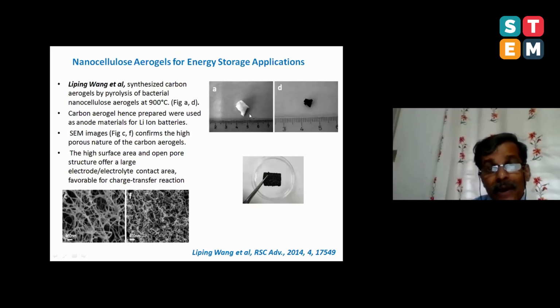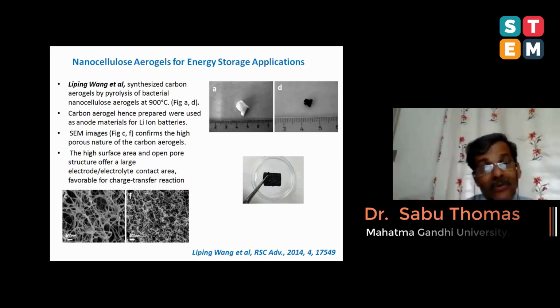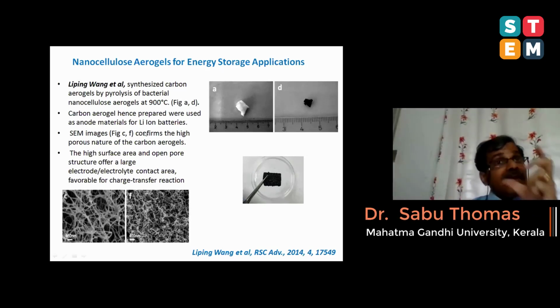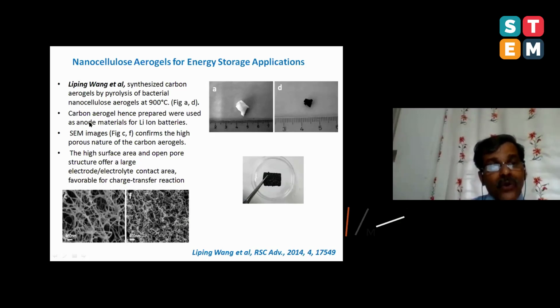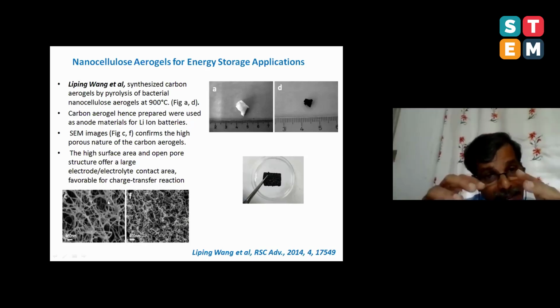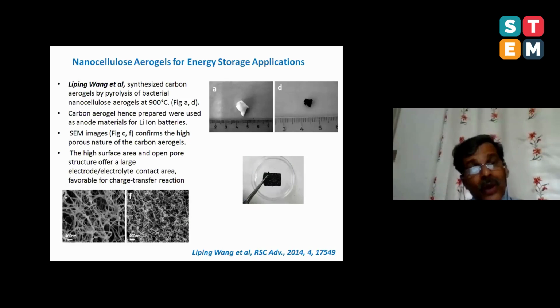And then they go for pyrolysis at high temperature, 900 degrees Celsius. When you go for pyrolysis, you transform everything into carbon. And this carbon is very beautiful because it is extremely porous. Professor Wang and group found that this is an exciting material for an anode for lithium-ion batteries. This anode is very light because of the porous structure. The interaction with electrolyte is extremely good because the surface area of this material is extremely high. Therefore, it can interact with electrolyte in the battery. Professor Wang said it's an excellent electrode, and he's working with different companies to scale it up.